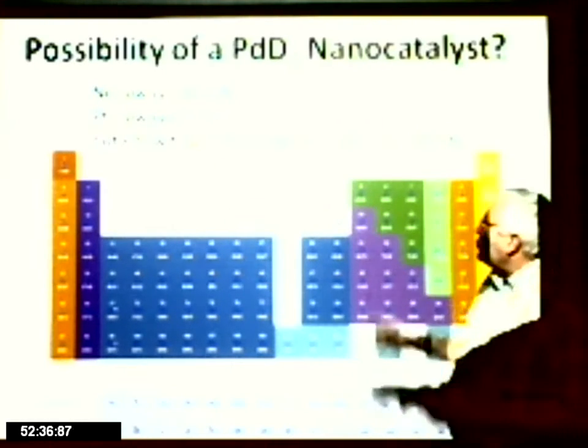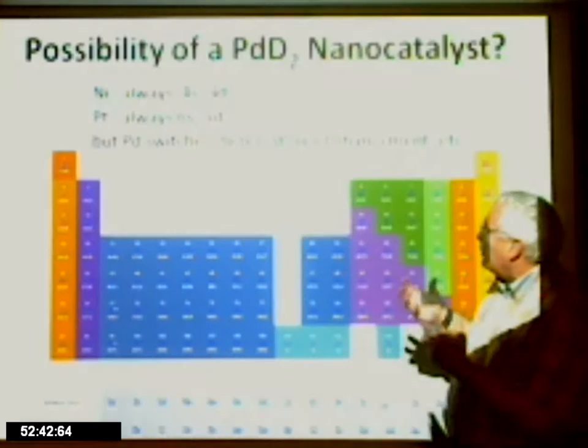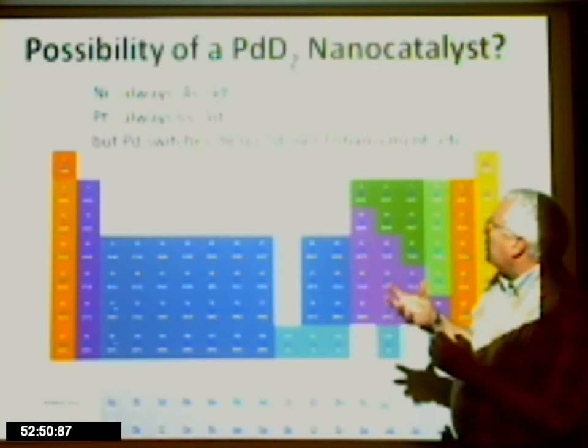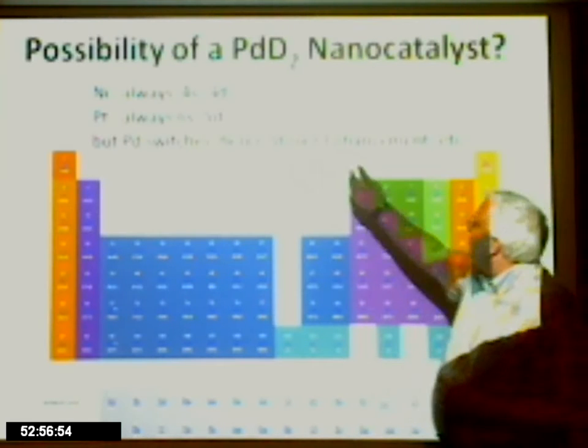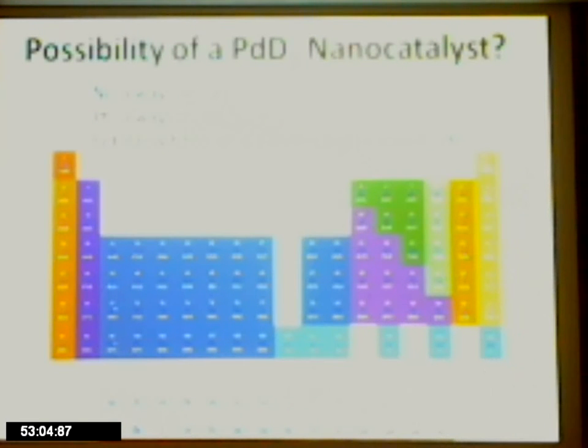Palladium, fascinatingly, has the ground state of platinum, but it's easily switched between that ground state and the ground state of nickel. And the thing that switches it, among other things that has been observed, are magnetic impurities in close proximity. This is called Stoner enhancement, and it gives rise to, effectively, a much higher effective moment of the impurity in palladium than in other metals. That's seen again because it can effectively induce a magnetic moment in the palladium metal that surrounds it. And this has been critical for these high-resolution thermometers that Steve builds and I used to build. But at any rate, the point I'm making here is that palladium is right on the edge anyway.